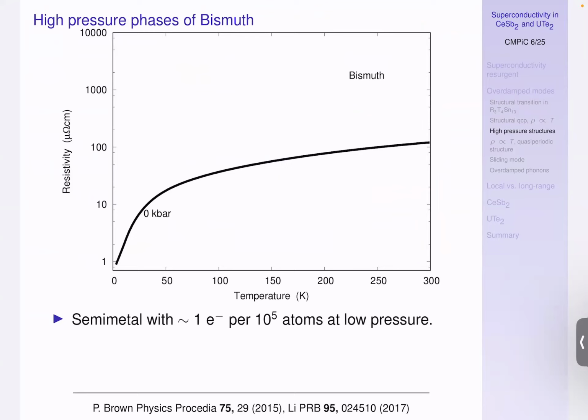It's not so easy to prove that you're dealing with overdamped phonons in a particular system, and it's also a question which immediately arises if you're theoretically minded: why would they be so strongly damped? What would dampen the phonons? They have to scatter from something, right? So they can scatter from each other, which basically means there's an anharmonic potential that they're moving in. So if there's a strongly anharmonic potential, fourth order terms, that introduces phonon-phonon scattering. That means two phonons can collide or a phonon can decay into other phonons. But those other phonons would have to have lower energy. So what if their spectrum has no lower energy phonons in it, how would that work?